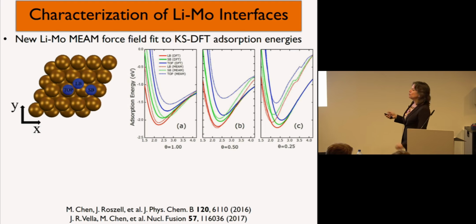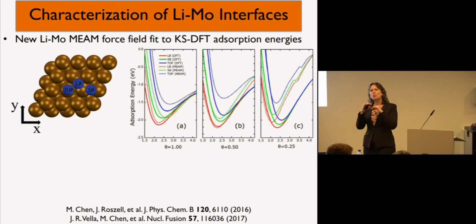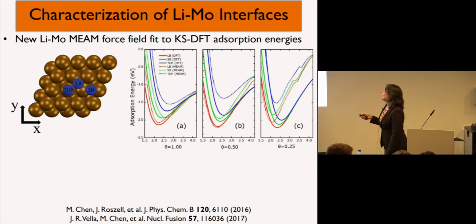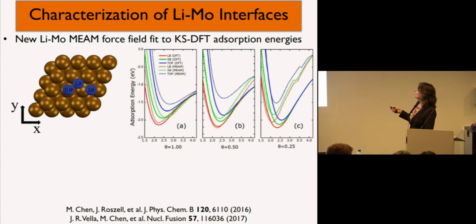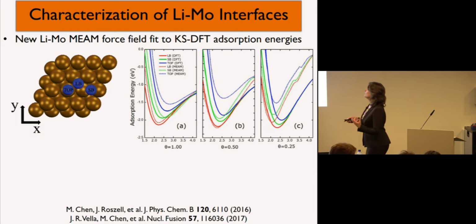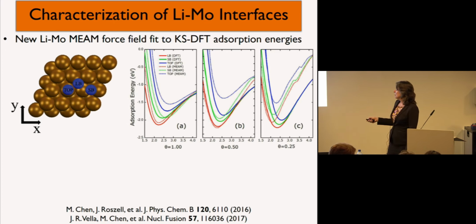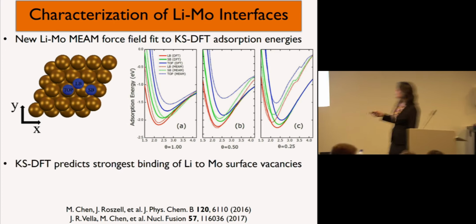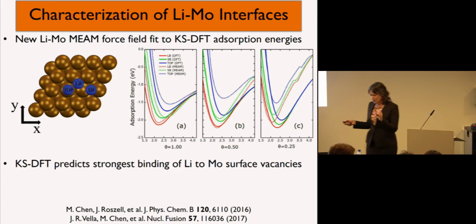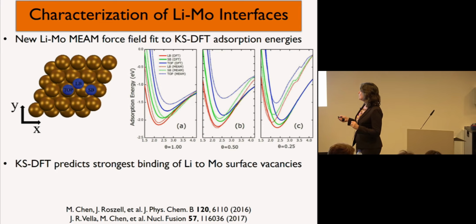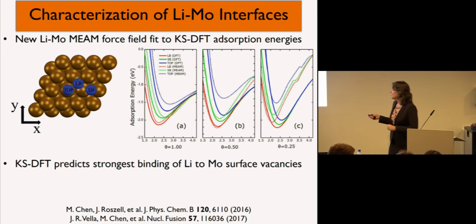And then, because we wanted to look at wetting, how well does lithium wet the molybdenum surface, we took those Kohn-Sham density functional theory results that are shown here, and we fit an embedded atom force field for lithium molybdenum. And what we found is we not just looked at pristine surfaces, but we also looked at surfaces that had molybdenum vacancies. And not surprisingly, when you have under-coordinated metal atoms, they're going to bind things more strongly. And so lithium will bind much more strongly to molybdenum vacancies.